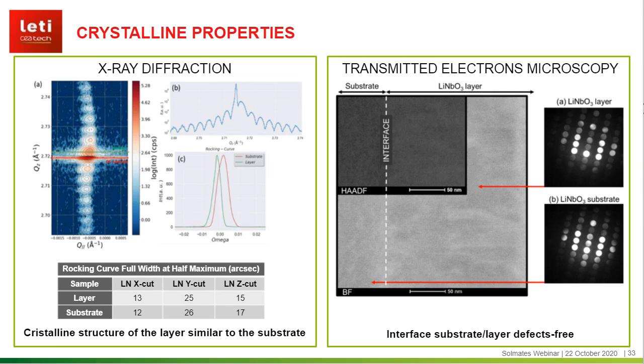The crystalline quality of the layers is excellent. Diffraction analysis performed indicates that we have narrow rocking curves for all the layers. Regardless of the crystal cut, we have low values of full width at half maximum. Thus, the crystalline structure of the layer is similar to the substrate for all the samples. We tested the X cut, the Y cut, and moreover, transmission electron microscopy analysis points out that we have a defect-free interface between the substrate and the layer, as illustrated here with a Z-cut sample.